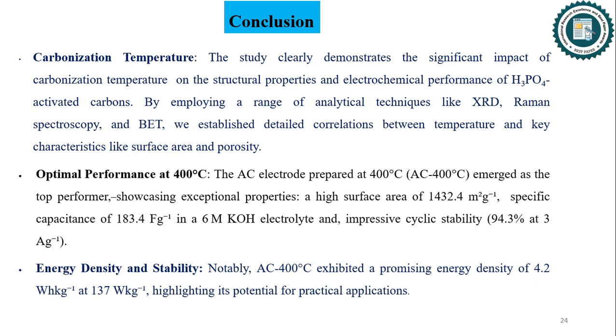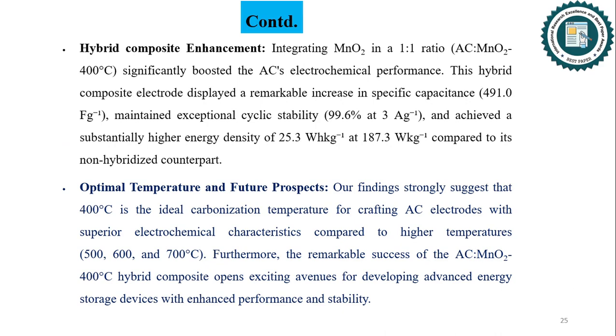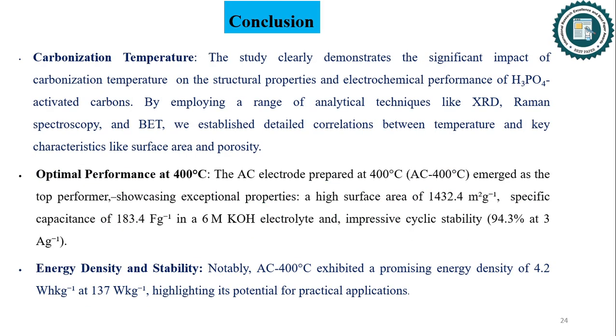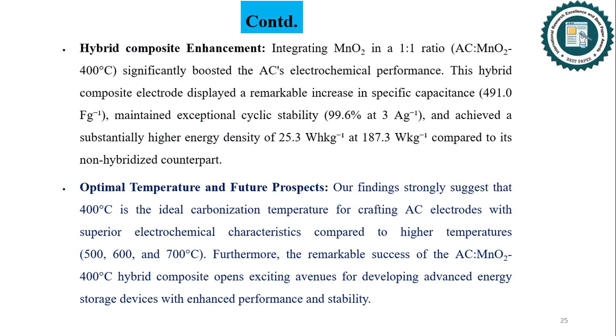Now we have come to the key points of the research. Our study demonstrates the pivotal role of carbonization temperature in shaping the properties of phosphoric acid activated carbons. Activated AC 400 degrees centigrade exhibits outstanding electrochemical performances with high surface area, specific capacitance, and cyclic stability, indicating its suitability for practical applications and suggesting exciting prospects for enhancing energy storage devices through AC MnO2 400 degrees centigrade hybrid composites.